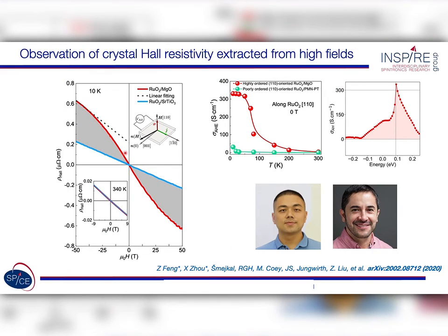The subtraction is a little tricky, because you still have to do the experiments in field, because the orientation of the Néel order parameter is not conducive to seeing the anomalous Hall effect. This is another characteristic of the anomalous Hall effect in antiferromagnets: depending on the orientation of the Néel order parameter, your symmetry will allow or not allow an anomalous Hall effect. This is in contrast to normal ferromagnets, where you would never be able to turn it off by symmetry.